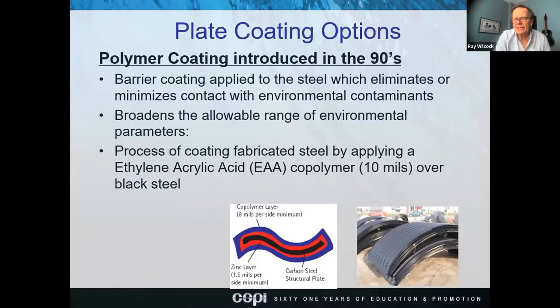Polymer was worked on back in the 90s. The reason it came into fruition versus the zinc is that we have certain water and soil chemistry conditions across the country where we require a much more robust coating. So it's a barrier coating that's applied to the steel. It eliminates or minimizes contact with the environmental contaminants. Things like road salts, soft water versus hard water, low resistivity versus high resistivity, and so forth. So it broadened the allowable range of environmental parameters, okay?